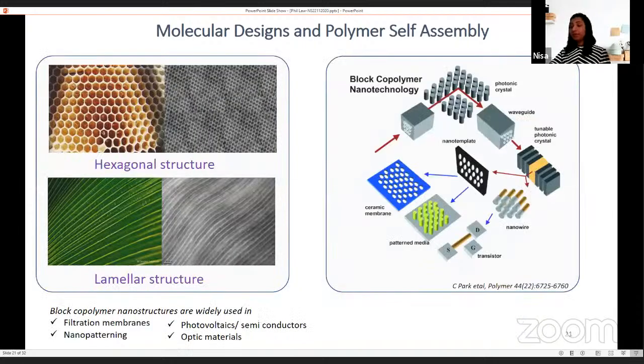Here are a couple of examples where we fabricated highly ordered nanostructures from direct self-assembly of block copolymers. We have fabricated honeycomb-like features. We also fabricated lamellar-like nanostructures. These structures are heavily used in nanopatterning applications and also for the fabrication of transistors. You'll be seeing some examples of ordered nanostructures formed by the direct self-assembly method.